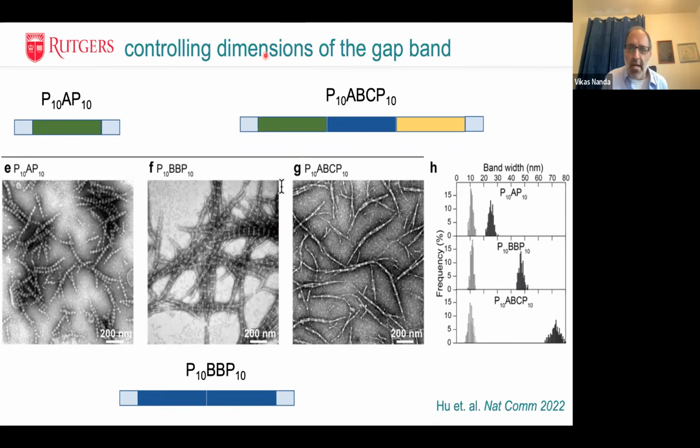So there was a question, does the V domain help in nucleation? Will the 3 helix stay helical after the V domain is cut off? The answer is yes. Once you're able to bring the 3 chains together, the helical domain does 2 things. One is it nucleates the folding of the triple helix, but it also controls the relative registry of the 3 strands.